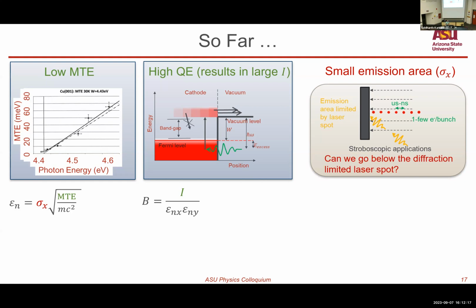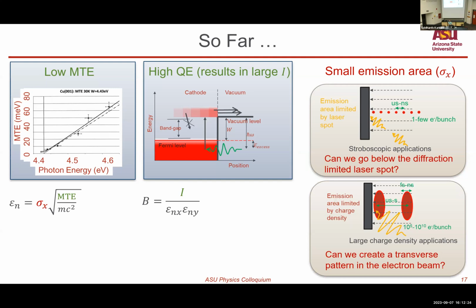Now, can we go below this diffraction limit of light? For large charge density applications, it's not limited by the diffraction of light. However, we can create a transverse pattern in the electron beam, which helps mitigate the space charge interactions, and you can achieve higher brightness using such things. Furthermore, several applications require electron beams that need to be patterned in a particular fashion. For example, in our compact X-ray free electron laser, we put in a lot of effort to generate a transverse pattern in the electron beam and then convert it into a longitudinal pattern. Can we make such patterns in the electron beam or in the light beam right from the cathodes?